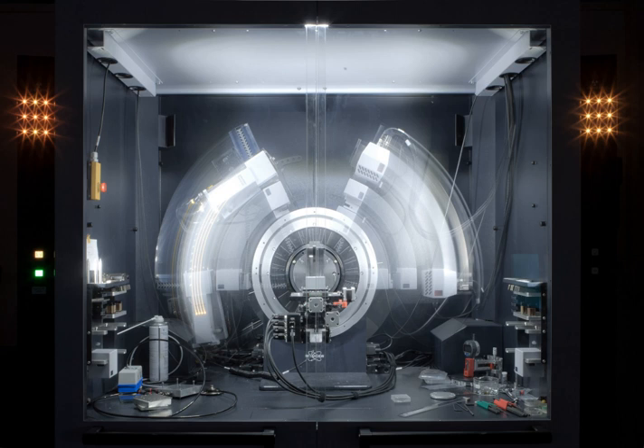Neutron diffraction is an excellent method for structure determination, although it has been difficult to obtain intense, monochromatic beams of neutrons in sufficient quantities. Traditionally, nuclear reactors have been used, although sources producing neutrons by spallation are becoming increasingly available. Being uncharged, neutrons scatter much more readily from the atomic nuclei rather than from the electrons. Therefore, neutron scattering is very useful for observing the positions of light atoms with few electrons, especially hydrogen, which is essentially invisible in X-ray diffraction.